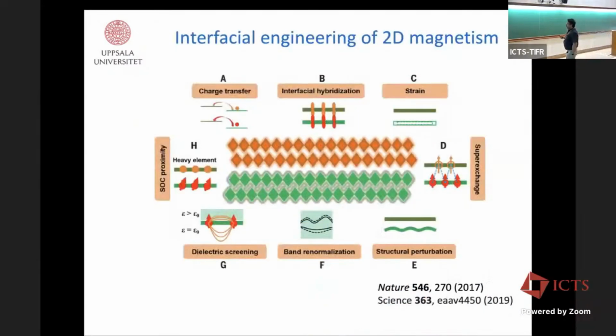An important thing, which was also mentioned in that talk, is how we engineer an interface of 2D materials. This is very interesting. You can have several processes: charge transfer or hybridization, strain, spin-orbit coupling, and proximity effect due to a strong spin-orbit coupling material. Dielectric screening is also important. For 2D materials, the screening is rather poor outside the material. So there are many such avenues by which you can control the properties of a 2D magnet by bringing another 2D material close to it.